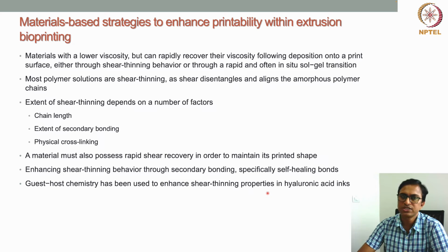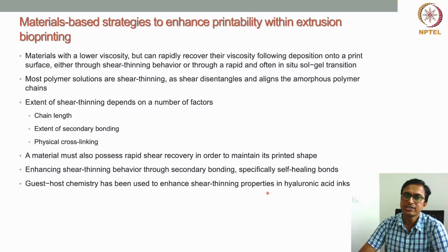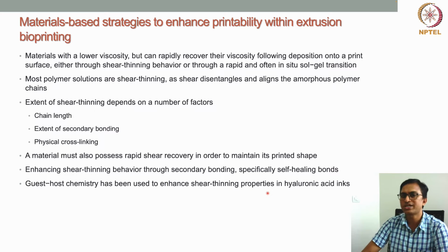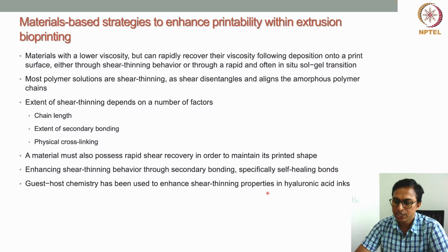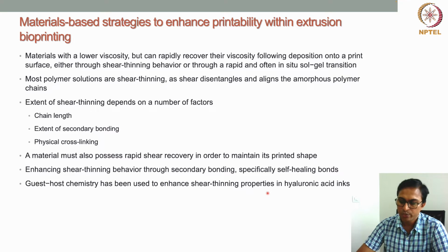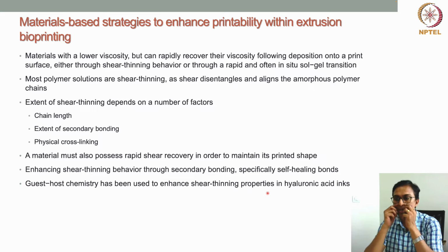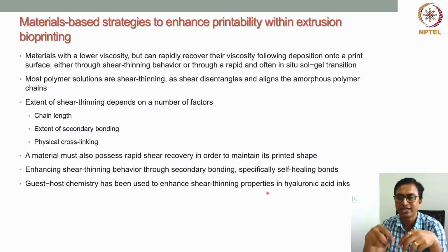Materials with lower viscosity can rapidly recover their viscosity following deposition onto a print surface, either through shear thinning behavior or through a rapid and often in situ sol to gel transition. In extrusion-based bioprinting, as we have discussed earlier, when the material is extruding through the nozzle, it is fluid, as in the sol state. But as soon as it comes out of the nozzle,